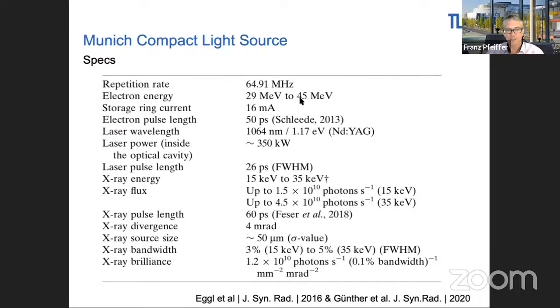So electron energy going up to 45 MeV in our case, laser power 350 kilowatts maximum, and altogether this brings us to an X-ray energy freely tunable between 15 and 35 keV. And these are flux rates. We are in the lower digit 10 to the 10 photons per second range, which is outperforming conventional lab sources, and more so at higher energies than at lower energies. But it's not really orders of magnitude more, it's somewhere nicely in between.